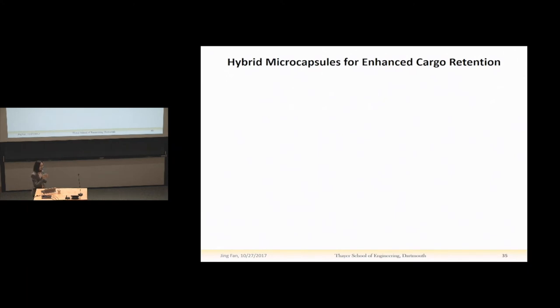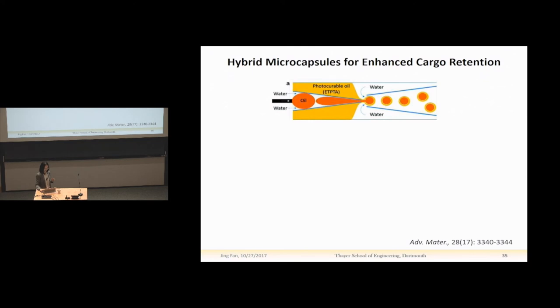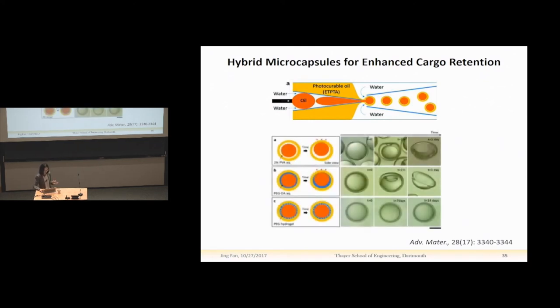We can also solidify the aqueous shell by using a pre-polymer solution to generate a thin layer of hydrogel. This gives hybrid hydrophilic-hydrophobic microcapsules. This is the schematic to generate the triple emulsions.